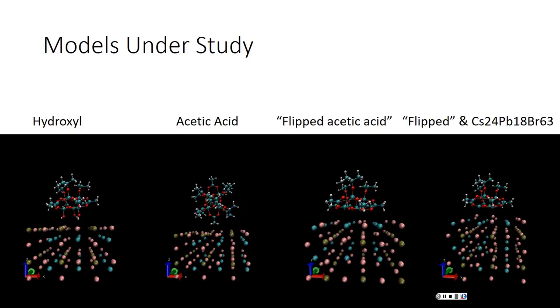So the ligands are mostly there to lower the barrier, in a sense, to make the charge transfer easier. But at the same time, you need to balance that with not allowing your charges to flow back across as they relax and then recombine, which would kill your efficiency in a solar cell. Very general. Yeah. Which applications are pursued specifically by Aaron if you were attending his presentations?